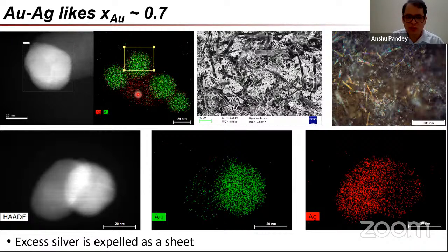So this is sort of what I'm showing over here. Here there are multiple gold-silver particles which are simply expelling the silver. Here, please note the scale bars are of the order of tens of nanometers. This is what another zoomed up profile actually shows, where you have a gold silver nanoparticle over here, simply expelling excess silver. And you can see from the elemental distributions that indeed there's a silver rich region located outside. These sort of structures don't form originally in the synthesis, but form a few hours later. So this seems to be an outcome of expulsion.